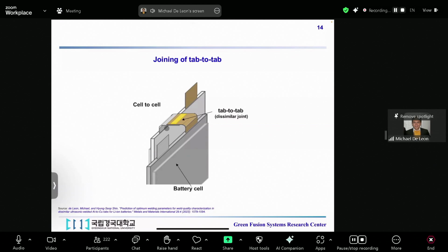This method allowed us to test only 9 sets of welding parameters instead of 27 sets for a full factorial design, meaning it dramatically reduced the time and resource cost. Also, using signal-to-noise ratios, we simultaneously prioritize 2 competing objectives. The first one is maximizing the mechanical strength using the larger-is-better approach. The other one is minimizing the electrical resistance with the smaller-the-better strategy. In addition, the Taguchi analysis can predict the outcomes, which can be validated through confirmatory experiments.